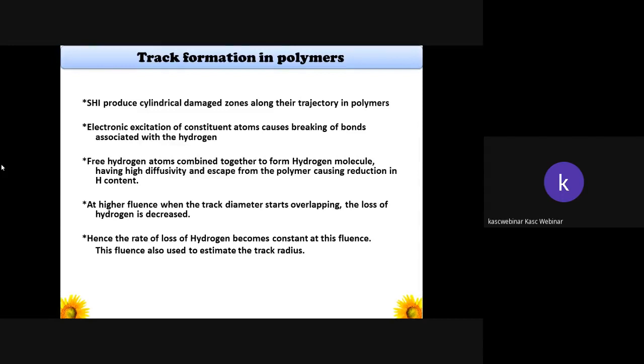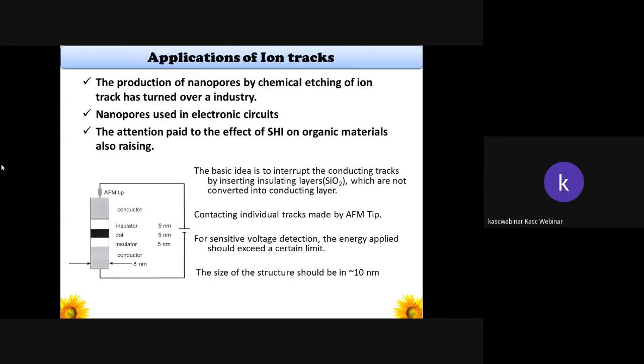Actually, the heavy ion produces a cylindrical damage zone along its trajectory in polymers. The electronic excitation of constituent atoms causes breaking of bonds associated with the hydrogen in a polymer material. The free hydrogen atoms combine together to form hydrogen molecules, which have high diffusivity and escape from the polymer chain, causing a reduction in hydrogen content. At higher fluence, when the track diameters start overlapping, the loss of hydrogen decreases. Hence, the rate of loss of hydrogen becomes constant at that particular fluence. This fluence is also used to estimate the track radius.